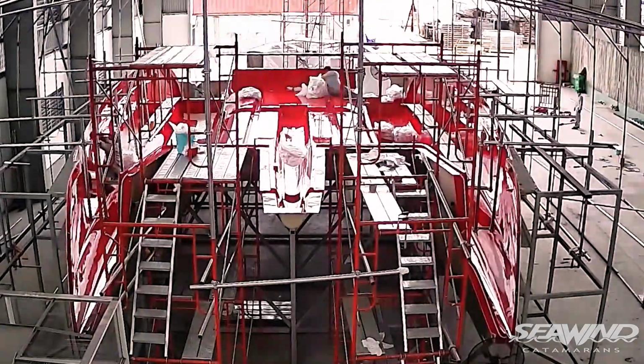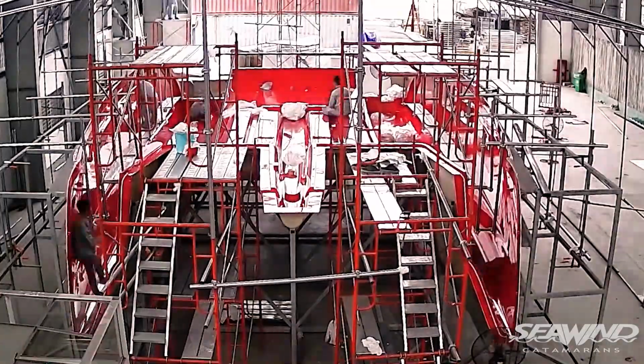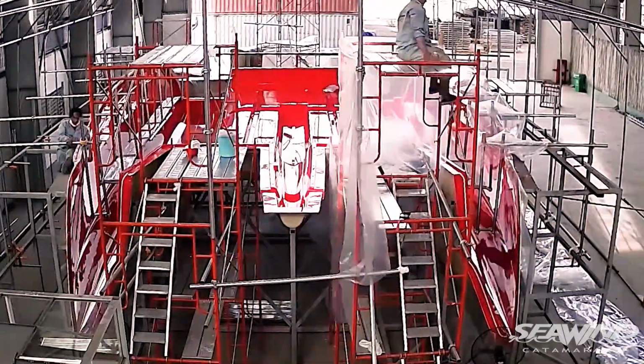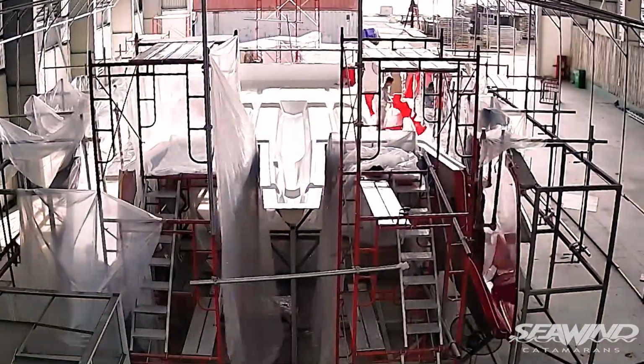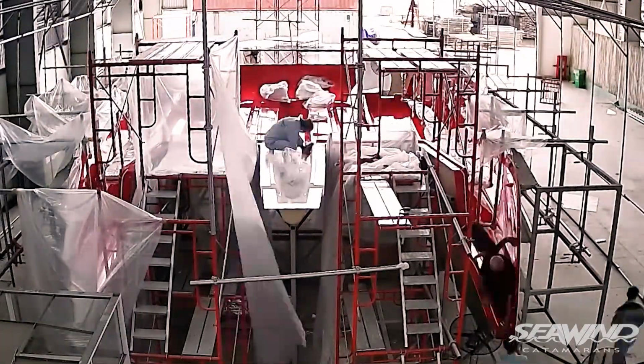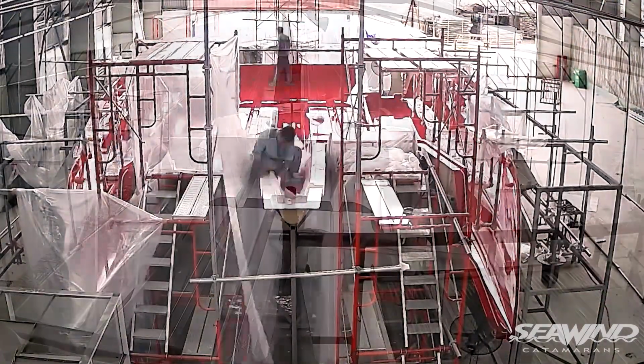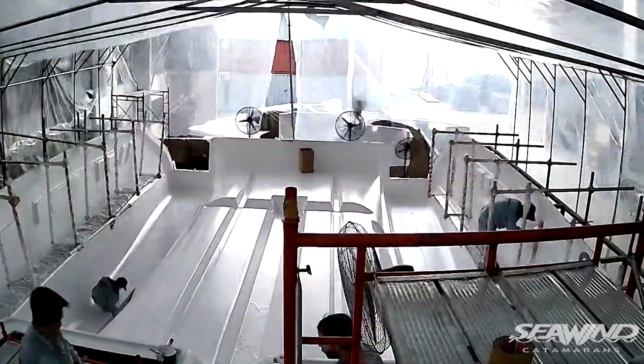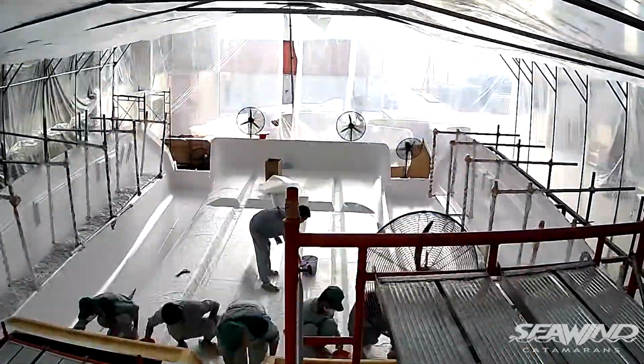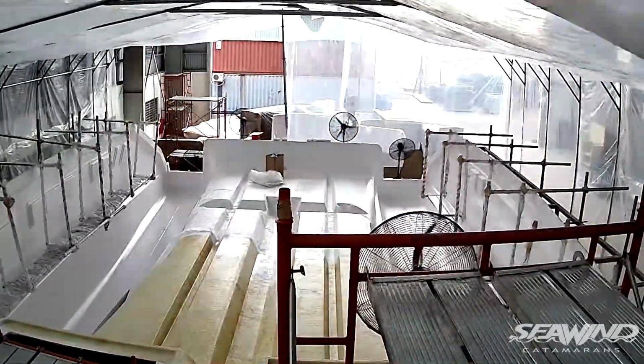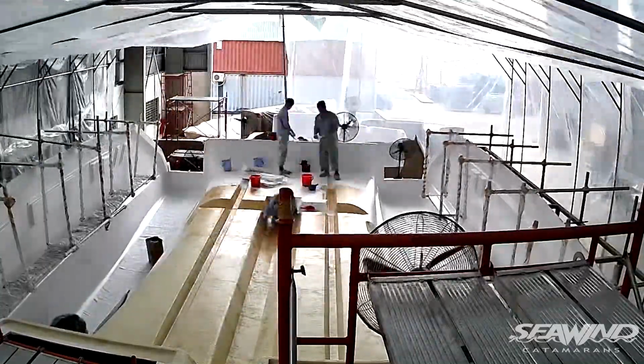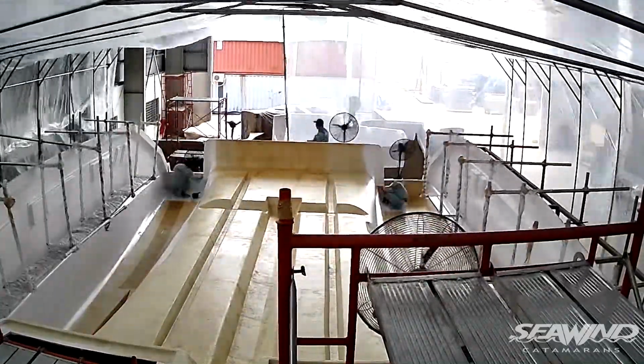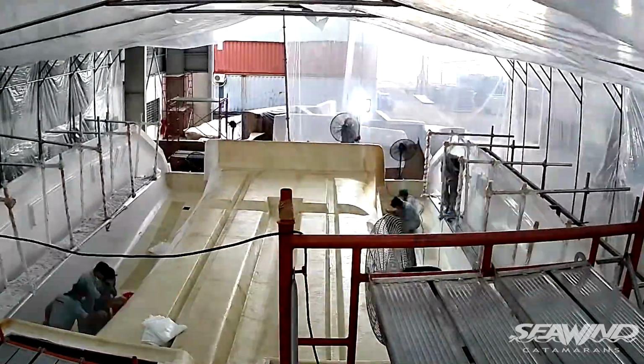The lamination process for the 1370, like all of our Seawind hulls and decks, is vacuum assisted resin infusion. This means that all the fibres are vacuum consolidated into the mould before the resin is introduced to the fibres by means of a vacuum, which gives us a thinner laminate using less resin and is therefore a stronger and lighter product.